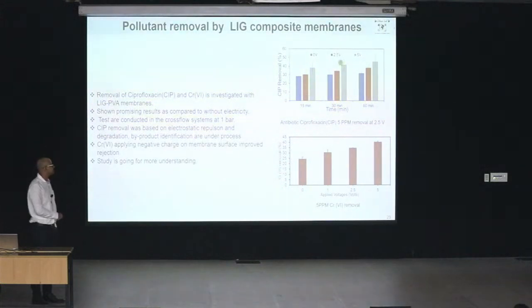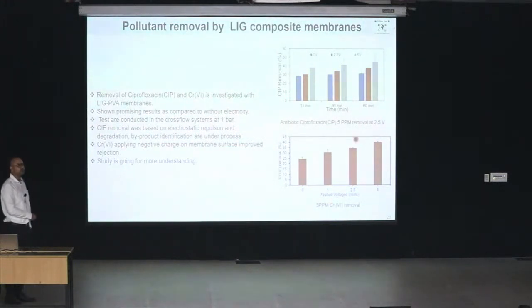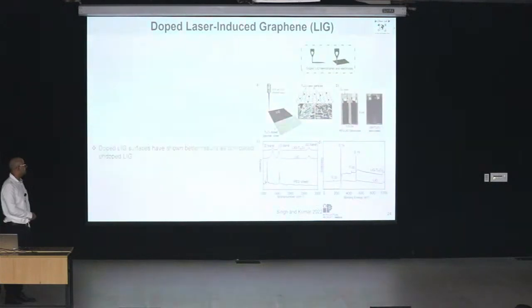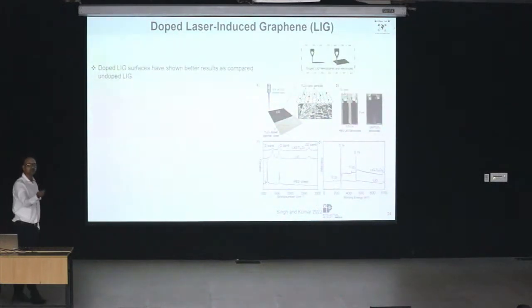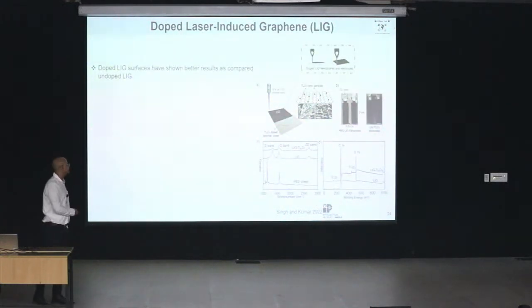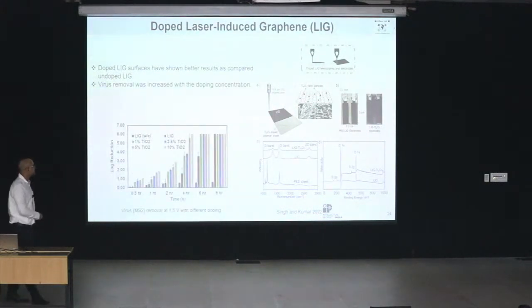We have also demonstrated that these membranes can effectively remove pharmaceuticals such as ciprofloxacin. Here you can see at different voltages we have effectively shown these membranes can remove different kinds of pharmaceuticals. Also, these properties of graphene can be enhanced if we dope with different kinds of metals. For example, we have recently doped with Magnéli phase titanium oxide, and we have shown enhanced properties for killing as well as other catalytic properties for degradation.